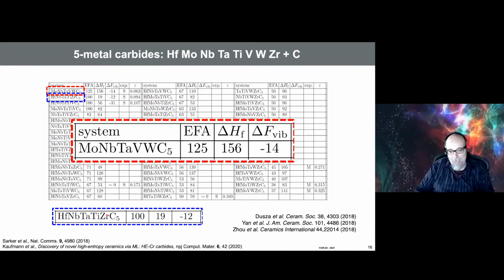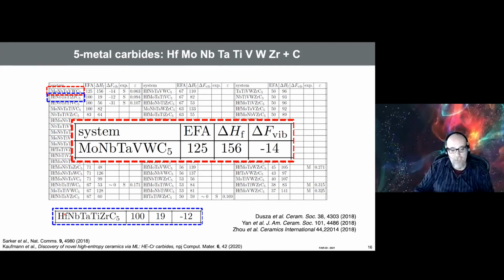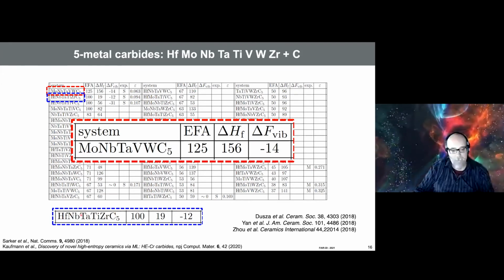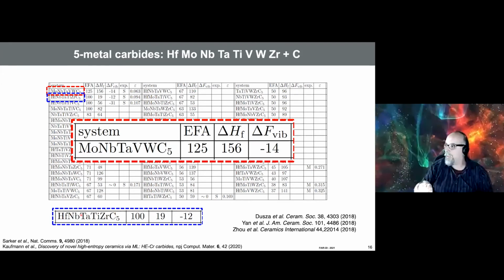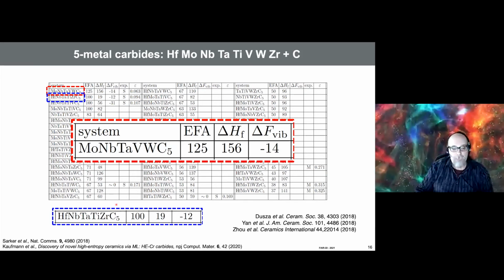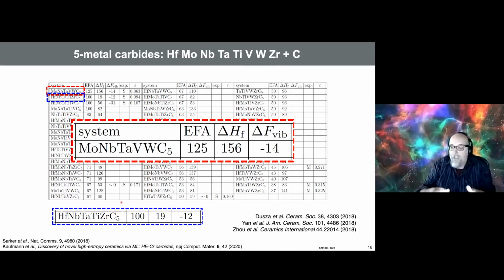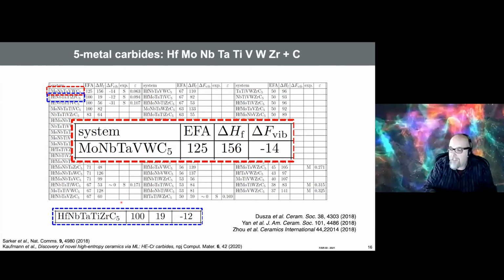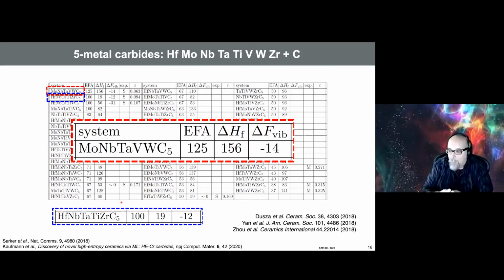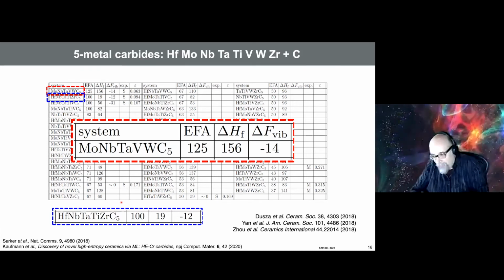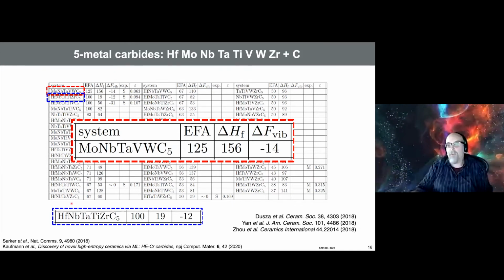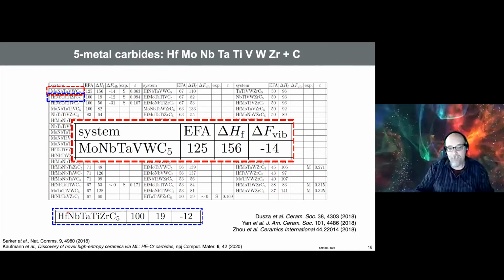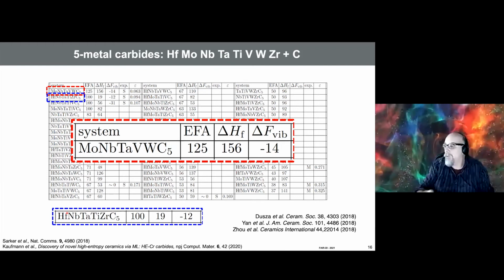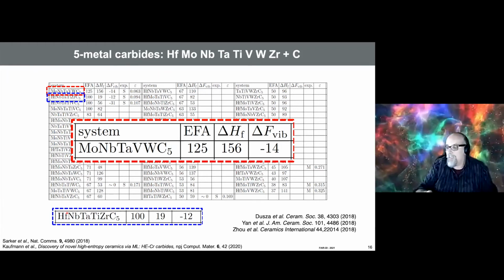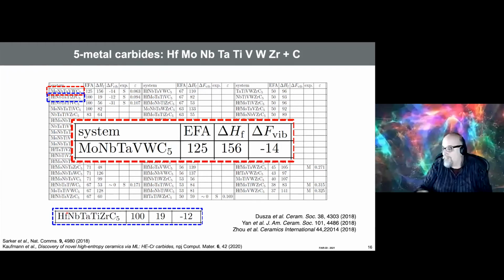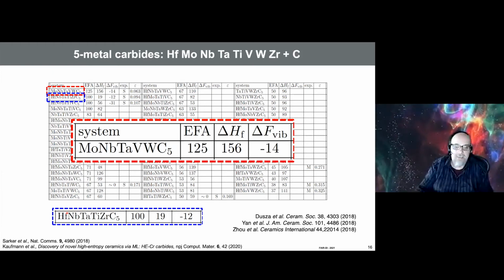This is a blah, blah, blah plus carbon. Okay, all these metal carbides, their precursors are cubic. So hafnium carbide, niobium carbide, they're all cubic. And guess what? You are mixing cubic tiles. What do you expect when you're going to have a cubic outcome? In fact, this was predicted a few months before us because this comes from phenomenological analysis, right? You say, well, I mix cubes. What am I going to get? I'm going to get cubes, right? With some strain and stress inside.